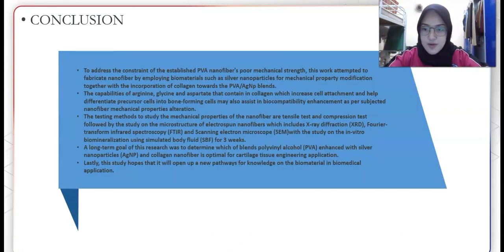In order to address the constraint of the established PVA nanofibers' poor mechanical strength, this work attempted to fabricate nanofiber by employing biomaterials such as silver nanoparticles for mechanical property modification, together with the incorporation of collagen into the PVA AgNP blends. The capabilities of arginine, glycine, and aspartate contained in collagen, which increase cell attachment and help differentiate precursor cells into bone-forming cells, may also assist in biocompatibility enhancements. The testing methods to study the mechanical properties of the nanofibers are tensile tests and compression tests, followed by the study on the microstructure of electrospun nanofibers, which include XRD, FTIR, and SEM, with the study on the in vitro biomineralization using simulated body fluid.